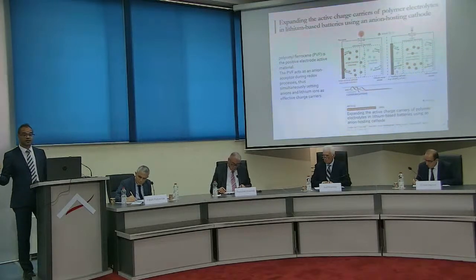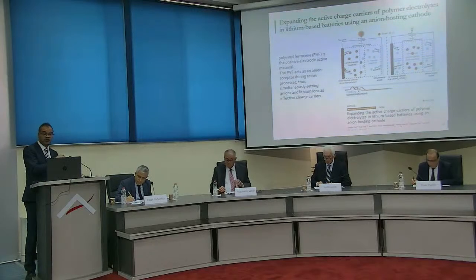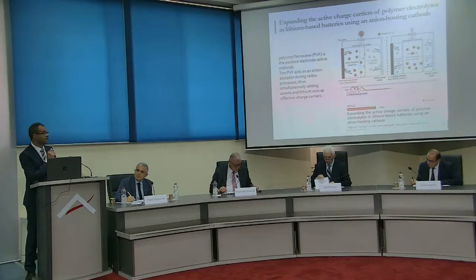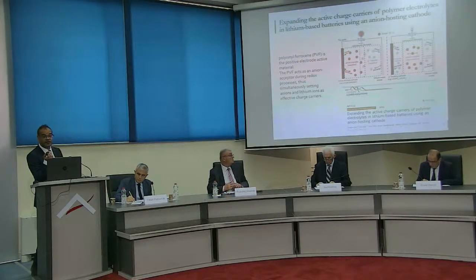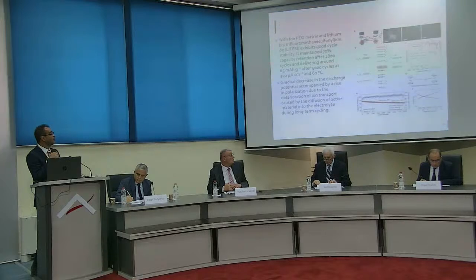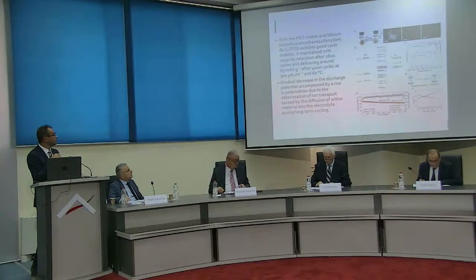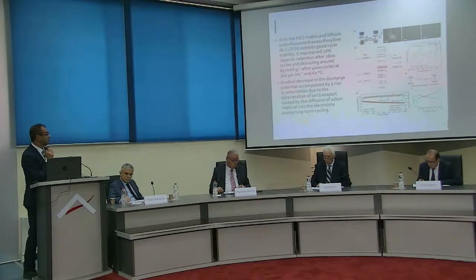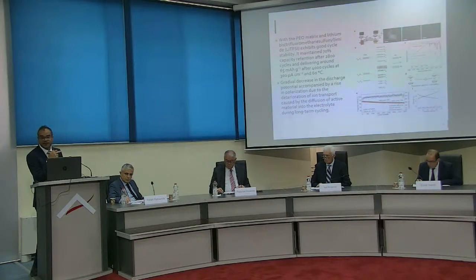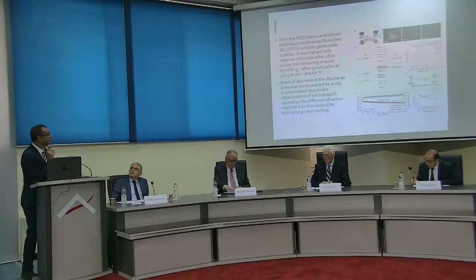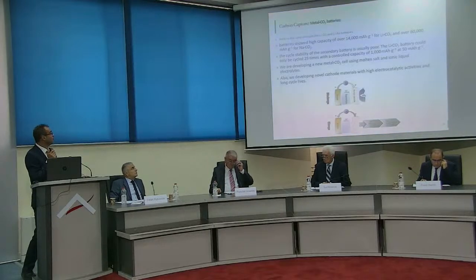So instead of transferring and storing the energy by lithium only, we use an anion as well to store the energy at the same time, which basically doubled the capacity of the battery and improved the conductivity a little bit, reaching, as you can see, around 4,000 cycles, which is quite a record for polymer batteries. Still struggling, because this concept, as good as it looks, actually promoted the dissolution of the cathode, which simply means we have a gradual decay of the battery performance. But we're still working on that. Hopefully we'll improve it in the future.